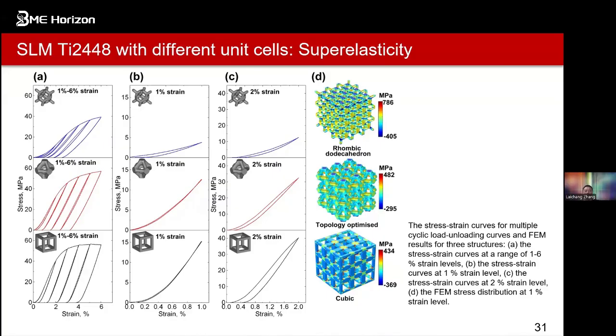So from here, you can see the cubes and also the topological one, mostly from the first step, they will fully recover. But for the rhombic one, this one can have some plastic deformation, because it is not fully restored. And then going further to 2%, you will see they go further, and also the cubic one goes even further. Okay, that's why you can see the structure of these things. But we still can compare these things.